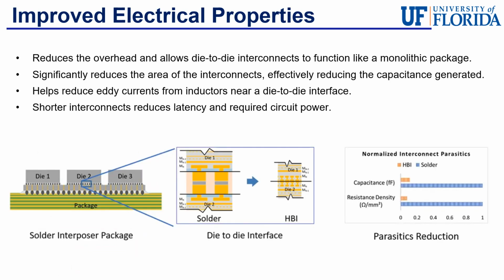A huge benefit of hybrid bonding is also the improved electrical properties that you get with the technique. Now, because the connections are so short and direct, it reduces the overhead, or the latency, as well as the consumed power to operate, and allows the interconnects to function like a single monolithic package. And the generated capacitance between the interconnects is also reduced by nearly 90% compared to solder, and the direct connections help reduce eddy currents that could be generated by inductors that are placed near the interface.